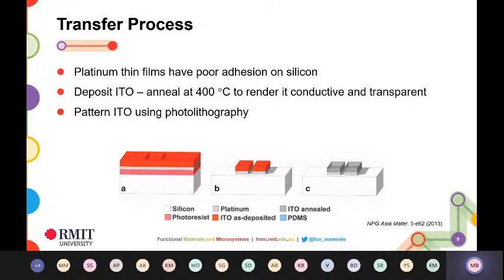So the premise of this entire transfer process is the fact that platinum does not stick to silicon. If you use platinum thin films on silicon, normally you use an adhesion layer like titanium or chromium or titanium dioxide. But in this case, we wanted to use that platinum as a transfer layer. So we put it down on silicon without that adhesion layer. Now, because you're still working on a silicon platform, what that allows you to do is deposit any oxide layer as you would normally, pattern it as you would normally, and heat it up as you require.